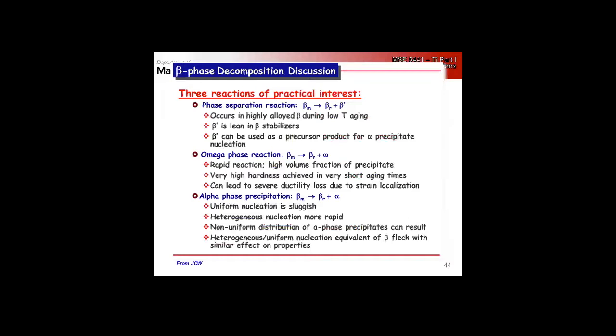So if we're going right from beta to alpha, what are going to be potent heterogeneous nucleation sites? So the beta grain boundaries for one, right? But is that something we're going to want? If we have a beta alloy, are we going to want to decorate the beta grain boundaries with alpha? No, right. We want to try and get as homogeneous a distribution as possible.